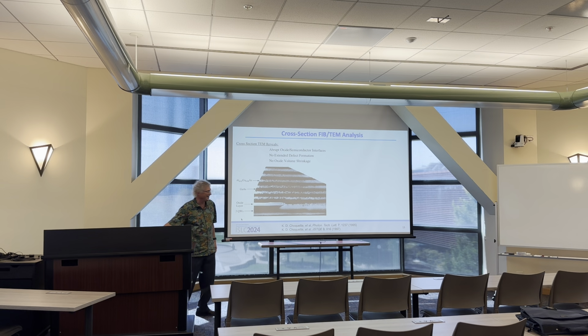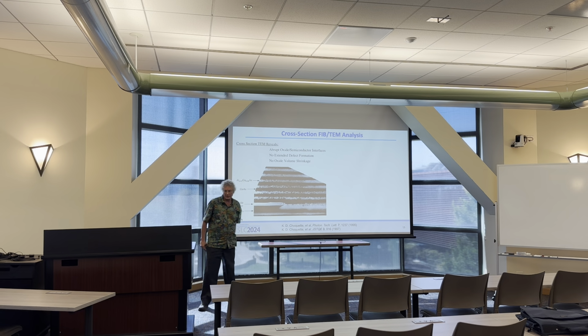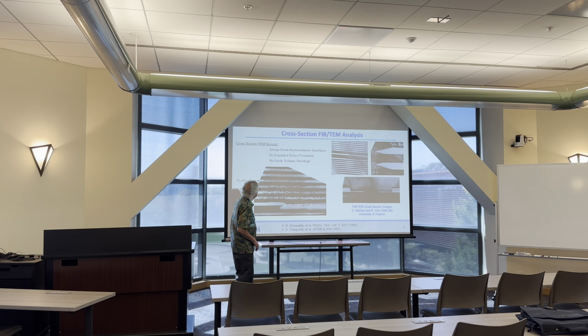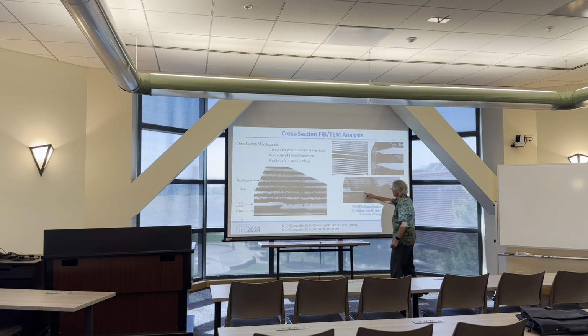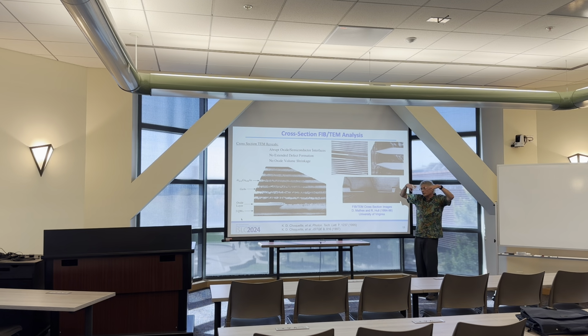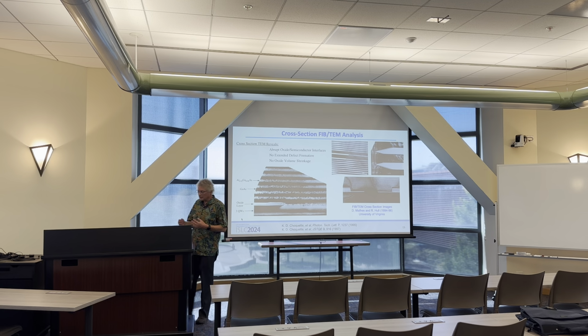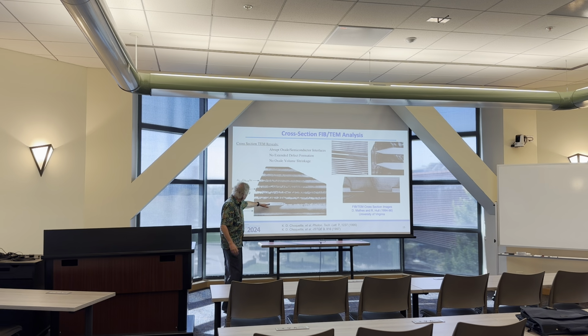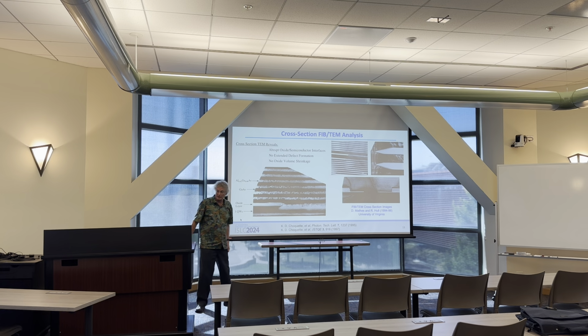So this is some of the first structures here. I know this is a terrible image because it's an image of a view graph that I have. But what you can see here is this is the oxide layer. There's 5 quantum wells here, and the key thing is there's no strain now. Then if you go ahead and control the compositions, you can play all kinds of games. We can oxidize various layers. This was meant to affect the capacitance. We can put thin layers on the null of the field. We can put tips. This is a structure where we're varying the composition in order to put a tip either on the null or the field. So we did lots of things basically. What we learned is that you really don't have to do much more than just try to make it as thin a layer as you can.